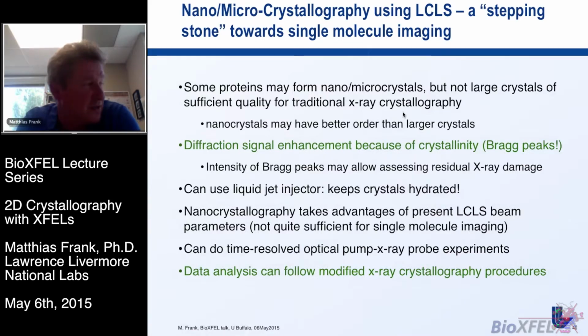The intensity of the Bragg peaks might also be useful to assess residual radiation damage. So just because we do diffraction before destruction doesn't mean there's no destruction at all. On some time scale there will be damage visible, and there's still a field of active research: how short does the XFEL pulse really have to be before we don't see any kind of damage anymore? And the times get shorter and shorter the closer people look.